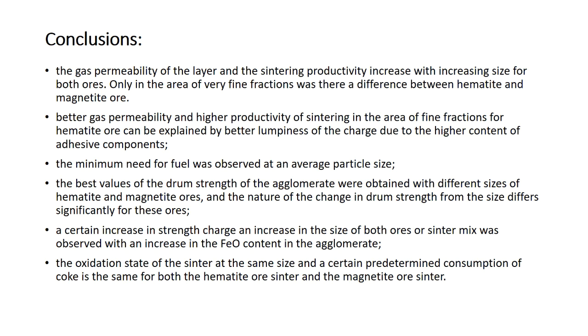The minimum need for fuel was observed at an average particle size. The best values of the drum strength of the agglomerate were obtained with different sizes of hematite and magnetite ores. And the nature of the change in drum strength with size differs significantly for these ores. A certain increase in the strength of the charge with an increase in the size of both ores or sinter mix was observed with an increase in the FeO content in the agglomerate. The oxidation state of the sinter at the same size and a certain predetermined consumption of coke is the same for both the hematite ore sinter and the magnetite ore sinter.